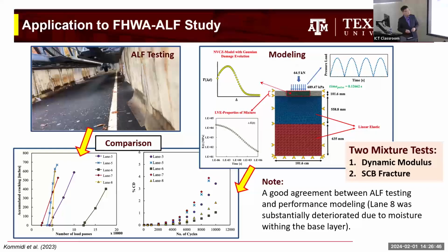And we adopted that method into a sort of validation using the data from FHWA through the collaboration. Here, this is their data from their testing. And then this is our simulation results from our computation. And we compare each other using the data, like the mixture data and the structural configuration with two mixture tests, dynamic modulus and SCB. And we got, in general, pretty good agreement between the two. So I think one-way coupling still works very well.